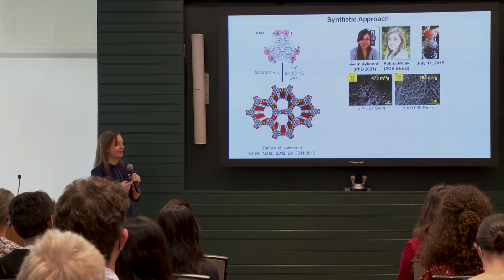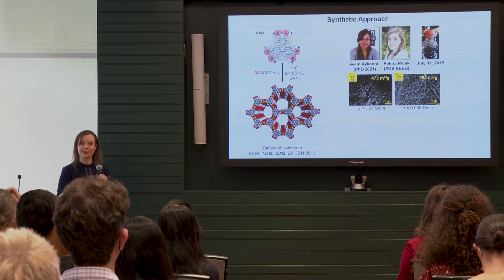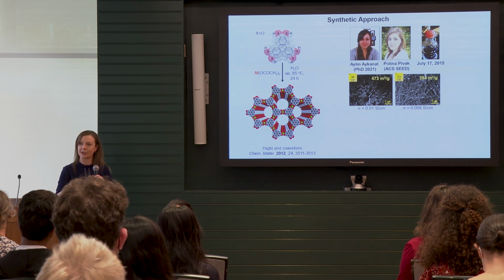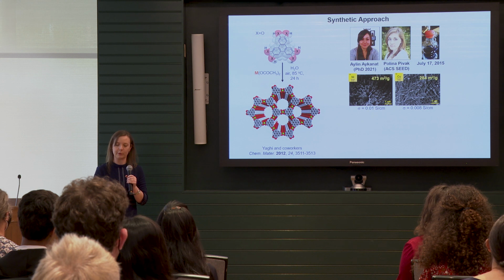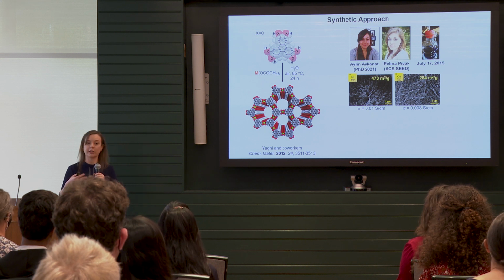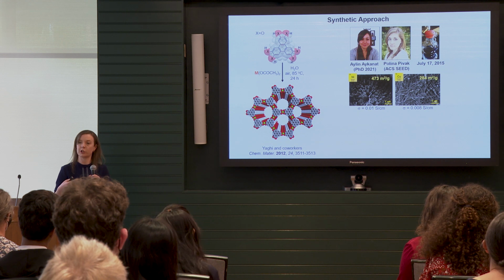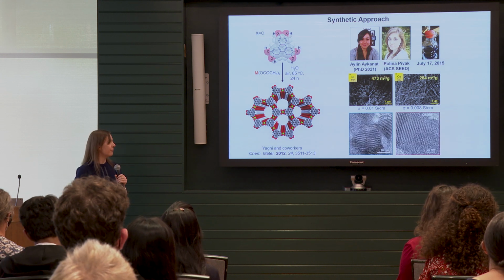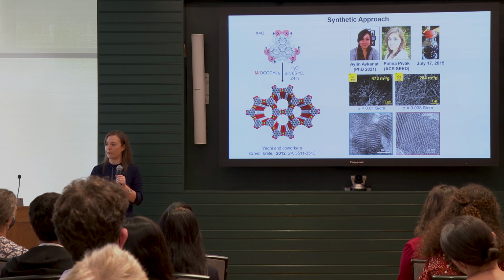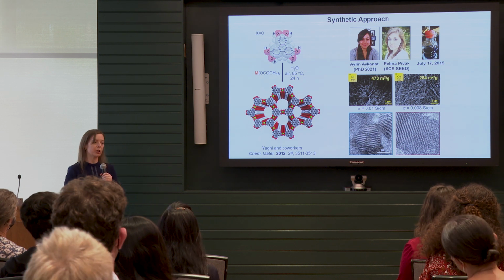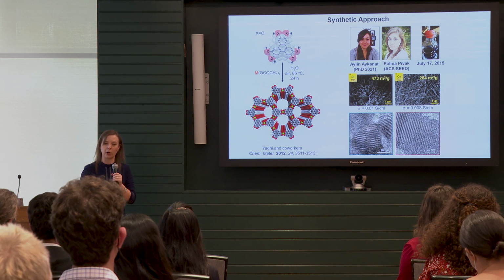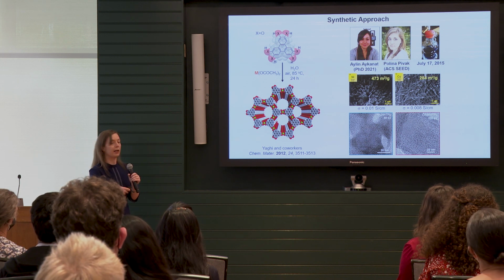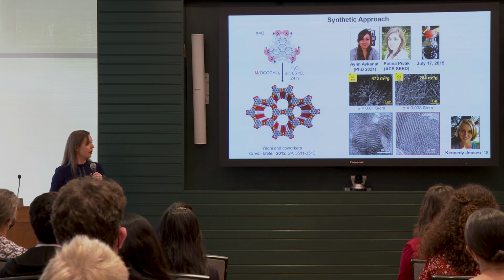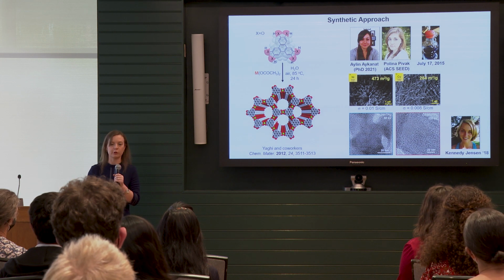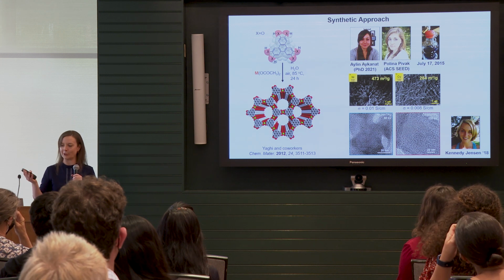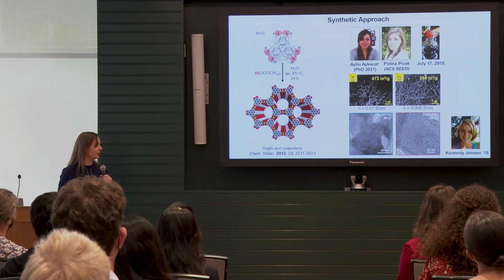I had never made these materials before I started here at Dartmouth. And when I did in 2015, about 2 weeks after we moved into the lab, one of my first students and high school students were able to run this reaction, and it works very well, very reproducible. So we're very excited about the involvement of undergraduates in this particular area of our research because the materials are so accessible. And in fact, we can take these nanowires and exfoliate them by sonication and obtain these transmission electron microscopy images that show the hexagonal porosity within the material as expected from its molecular structure. And that particular image was taken by an undergraduate who was a former WIST student and then went through the entire UGAR program at Dartmouth, Kennedy Jensen, who's currently at Geisel.